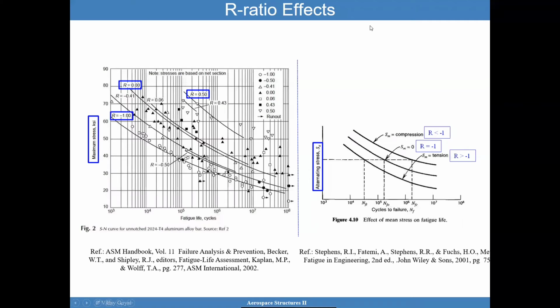We could study this. So let's look at the alternating stress in the right figure. For constant alternating stress, you're going to see here that for a mean stress that's in tension, the number of cycles to failure is less. When I go to fully reversible, a little bit more number of cycles, and when I go with a mean stress that's in compression, then I get even a higher number of cycles. So the effects of mean stress are quite significant and need to be considered in many situations. On the left-hand side, we see the SN curve for unnotched aluminum alloy bar, but here the plots are given in terms of maximum stress. And so again, like I said before, a lot of test data in the literature is given to you many different ways.